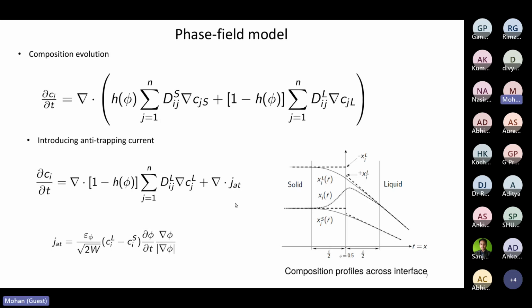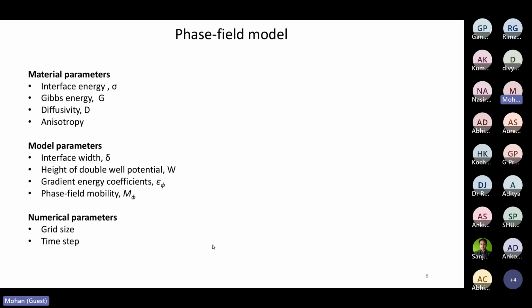And as we have discussed in the previous talks, because of the diffuse interface nature of the models, if you try to increase the interface width of these diffuse interfaces, a fictitious solute trapping comes up, which will be handled through anti-trapping currents, which has been explained very well in the previous talk also. So this is a similar function which will be used in the KKS model. Right now the KKS model is for multi-phases and multi-components. So these terms are generalized into the multi-phase or multi-component descriptions.